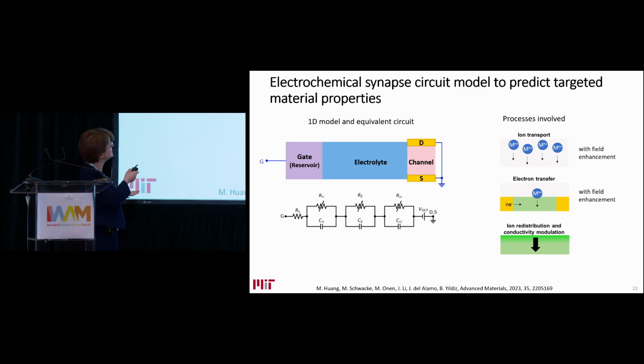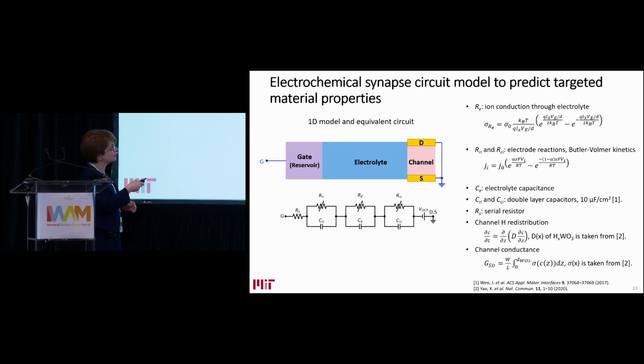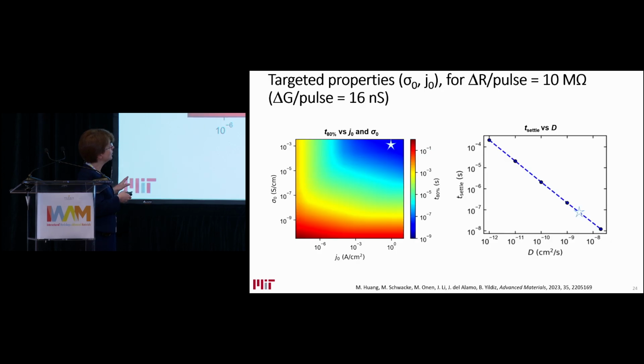And for this, we have constructed a physical 1D model, an equivalent circuit model of these battery-like devices, where we are considering the ion transport with field enhancement, of course, interface charge transfer reactions, as well as ion diffusion and conductivity modulation. The models we adopt for these circuit elements come from existing literature, the well-established field-accelerated ion transport. For interface reactions between an insulator and a semiconductor, there is no well-established charge transfer model. So just to start with, we have adopted the Butler-Volmer kinetics. And of course, ion diffusion reactions and the effect on the semiconductor conductivity are all included in this model, to map out what should be the electrolyte conductivity, interface charge transfer coefficient, and channel diffusivity for any ion, so ion agnostic, to put us into this tens to hundreds of nanosecond regime.